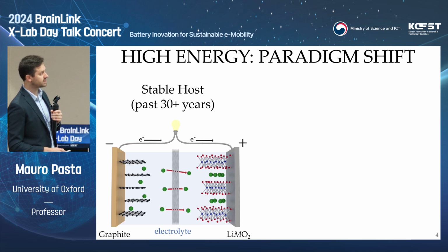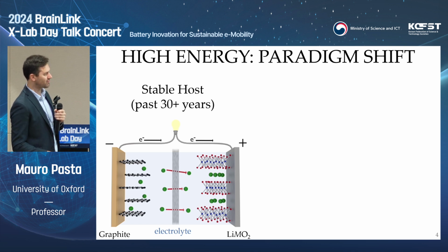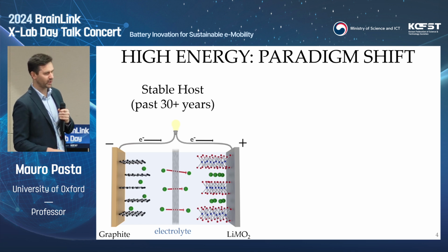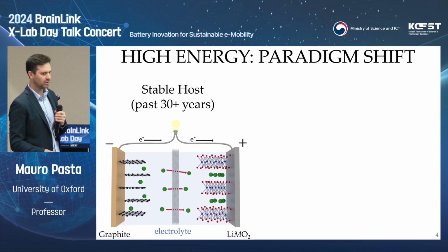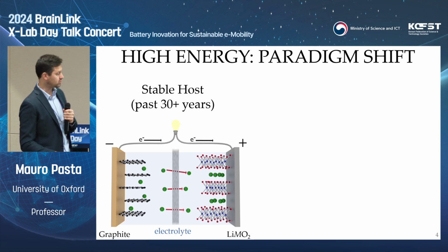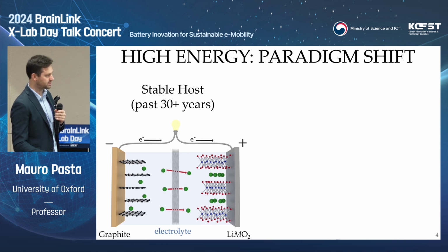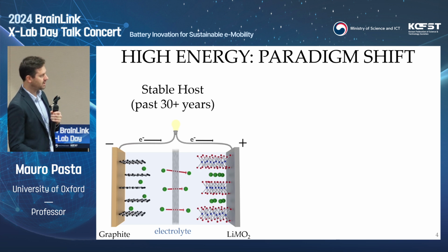So for the past 30 years, again, we use what I like to refer to as a stable host structure, where your active material doesn't really contribute to storing energy. They provide a scaffold for lithium ions to be intercalating reversibly. So graphite as a negative electrode, a transition metal oxide or a phosphate as a cathode material, with a liquid electrolyte in between.